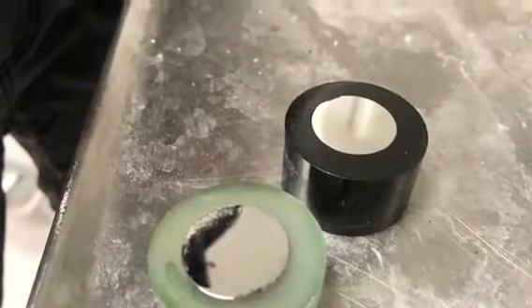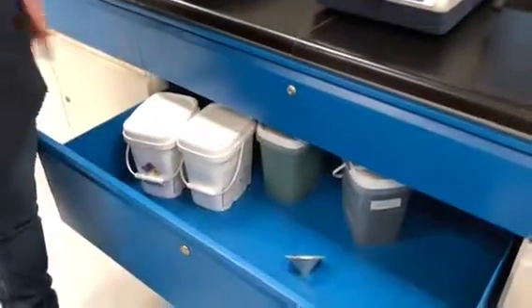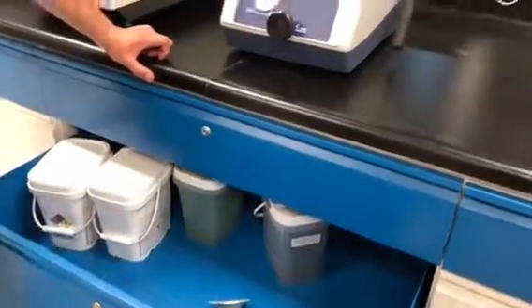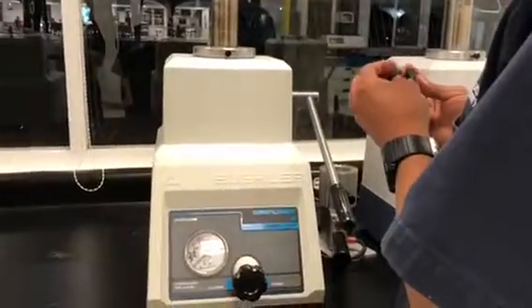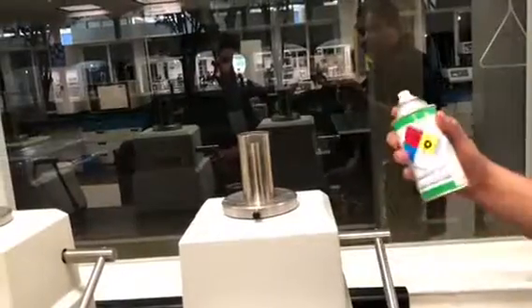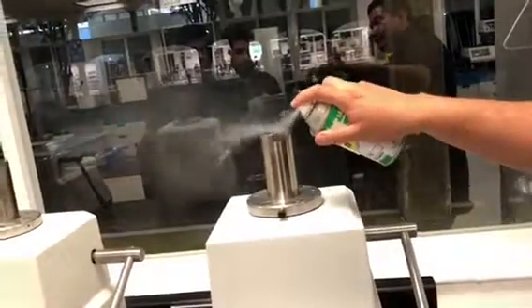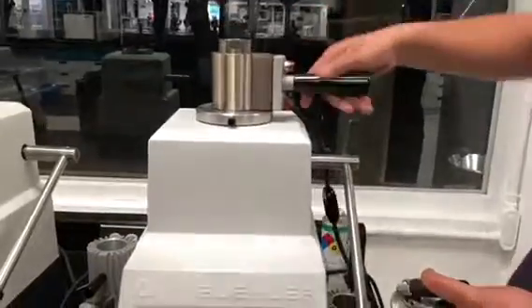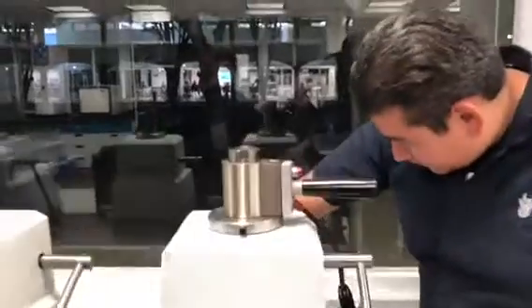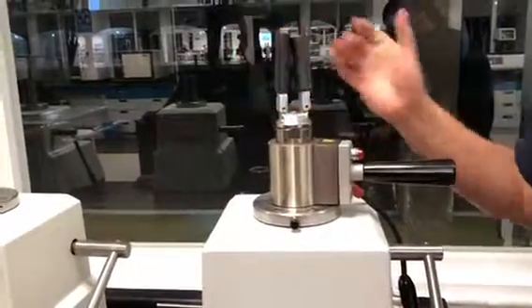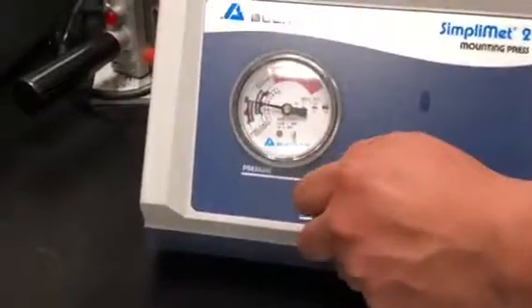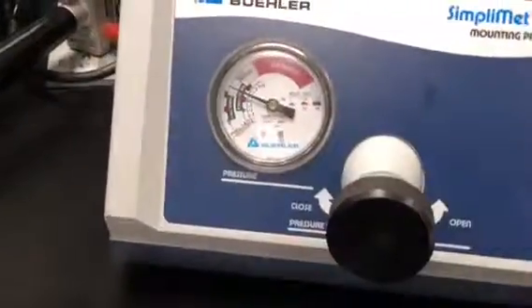To do this, a metal sample must be placed into phenolic powder with a stuffer. The sample is placed, keeping it centered after the mold release has been applied. Then, the resistance is applied and the cover is closed. Pressure is pumped until the red dot is on. This must be maintained for 10 minutes.